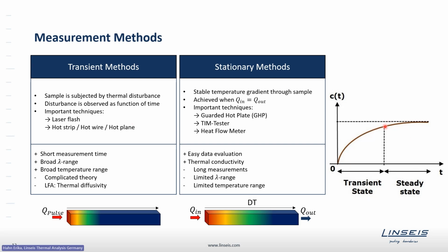The transient state is directly looking at when bringing in the thermal disturbance into the material. The steady-state methods just take a bit longer, and we wait until there is a constant heat flow through the sample. This looking directly at bringing in the thermal disturbance also gives the advantage of the transient measurement methods, where we have a short measurement time. Additionally, an advantage of these transient methods is typically that a very broad thermal conductivity range can be covered within one method. Also, a broad temperature range can be established.